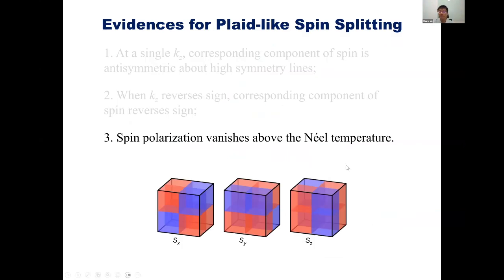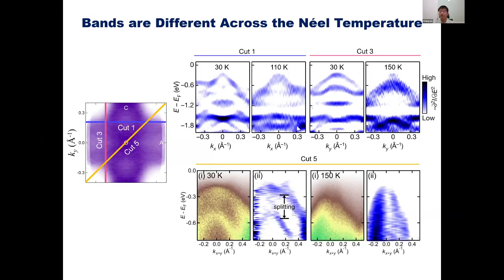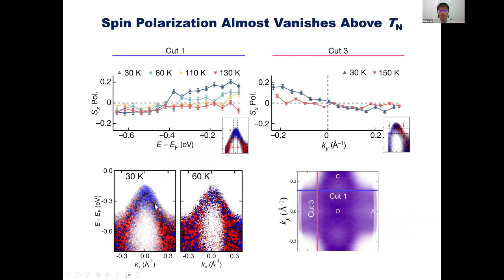The third evidence for the plaid-like spin splitting has to do with temperature. When we are at the low temperature phase, the spin is very apparent here. When we approach the high temperature paramagnetic phase, the spin becomes weak and eventually disappears when it goes above the TN. This one is 30 Kelvin and this one is 150 Kelvin. Remember the TN is 87 Kelvin here. So we can see that above 87 Kelvin, it has almost no spin polarization.